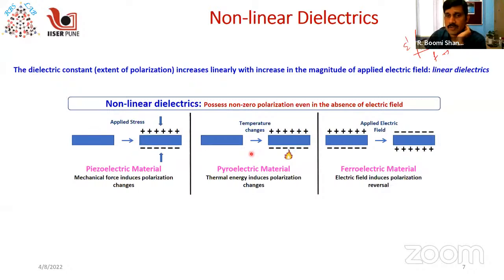Okay, so the second class of compounds are called pyroelectric materials, in which if you change the temperature of your measurement, the polarization changes. Okay, so that means the material is dependent upon thermal changes, and therefore they are called pyroelectric materials. Okay, if these pyroelectric materials show a reversibility of the polarization, that means that if you reverse the electric field, the polarization changes its direction. So the polarization which is pointed upward in the first cycle of measurement will now point towards the lower direction, and that will be called switchable polarization. Okay, and those materials are called ferroelectric materials. Therefore, electric-field-induced polarization reversal is experienced for ferroelectric materials. So the nonlinear dielectrics are three classes: piezoelectric, pyroelectric, and ferroelectric.